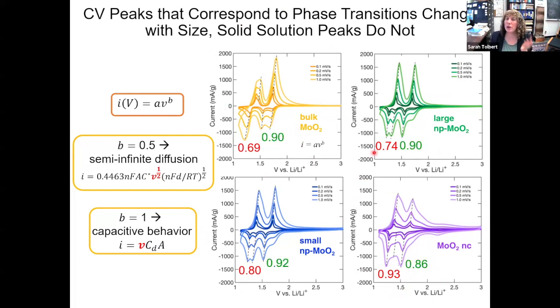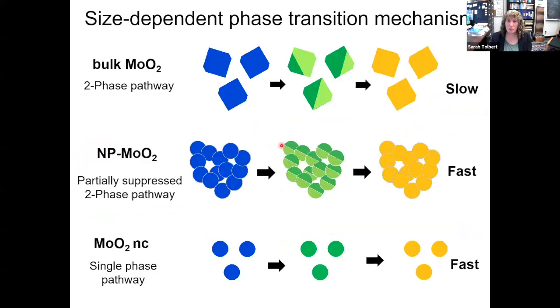And so when we have a kinetic limitation, we look like a battery. When we don't have a kinetic limitation, we look like a capacitor. Okay, what does that tell us about the way these things charge? In bulk materials, we have two-phase coexistence where we have phase boundaries and motion of the phase boundary, and that makes bulk materials slow. Nanocrystals are really fast because they show that solid solution behavior.